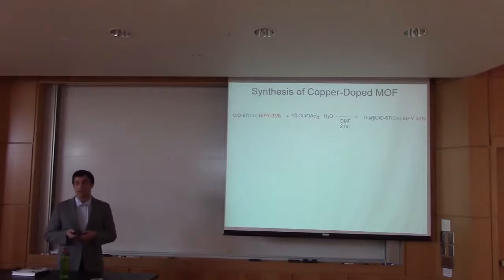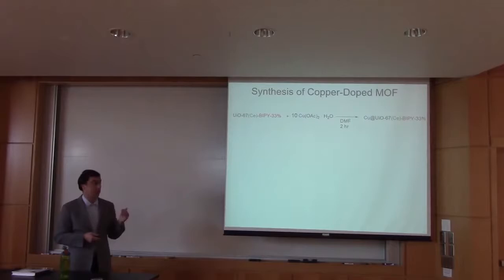The next step, we're going to add that copper salt. So we're having that same pale yellow MOF precursor, to which we're adding this copper(II) salt, copper acetate, in excess. It's this bright blue color. We're going to dissolve that salt in DMF and mix for 2 hours with our MOF precursor and obtain our copper-doped MOF, which is great.